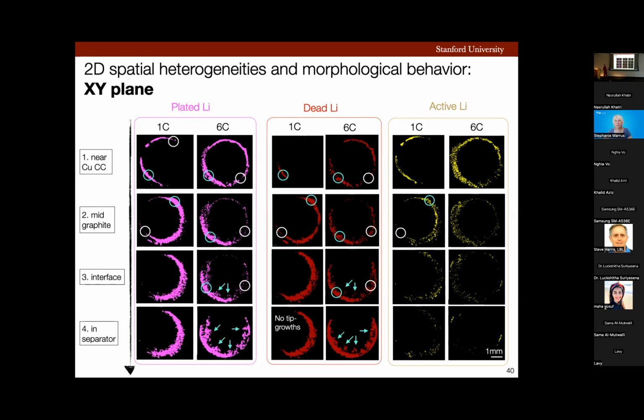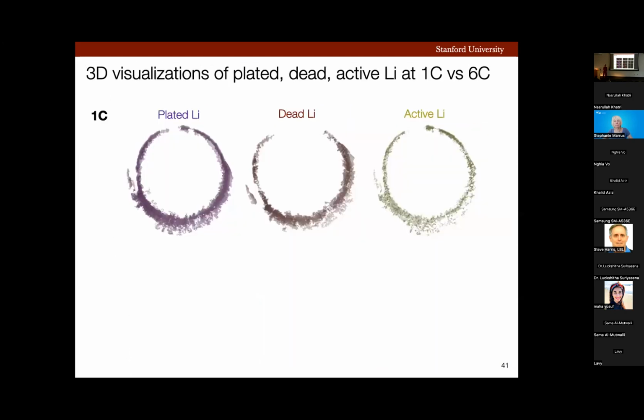However, by comparison, if you look at 1C, we didn't observe any tip growths. We only observed this mossy root-growing morphology in a crescent moon-like geometry. You would also notice one thing, that active lithium is the highest near the current collector and lowest in the separator, which is in agreement with what we observe in the cross-sectional images. Now let's look at the 3D visualizations of plated dead and active lithium at 1C.